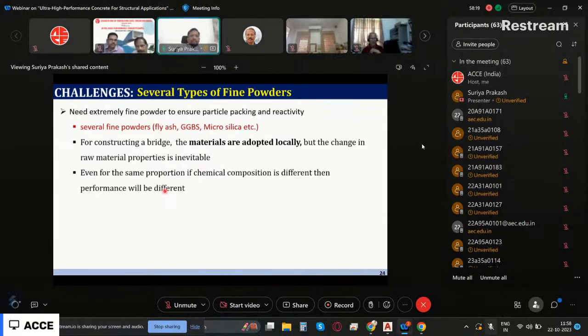And we also need to use several types of fine powders. Okay, we need extremely fine powder to ensure particle packing and reactivity. Now, what are the different types of fine powders? Fly ash, GGBS, microsilica, all of them have to be readily available. And for constructing a bridge or something, the material should be sourced locally. But then when you are using locally available materials, the material properties will change depending upon where I am getting the material from, right? Fly ash characteristics.